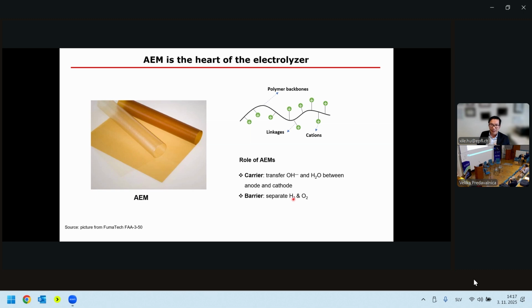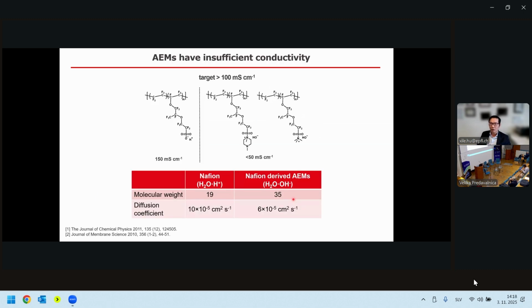Now, in this case, there are many challenges on this membrane. First of all, it does not have sufficient conductivity, because conductivity is an important criteria for these energy devices, and this can be understood if we consider the molecular weight of this anion. Okay, now if we compare to a proton conducting material like Nafion, it's conducting solvated proton. Okay, now we know solvated hydroxide actually typically have effective molecular weight that is much higher than that of proton. So the diffusion coefficient by itself is already about half of the proton. That makes it that the conduction itself is less efficient.